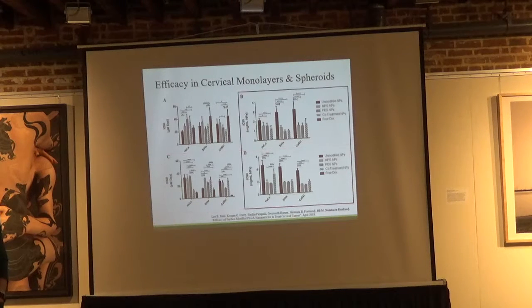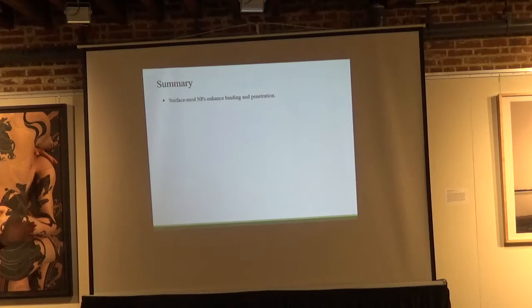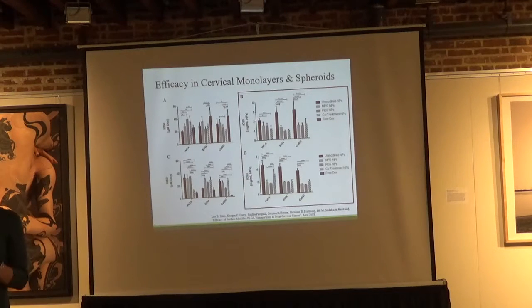And one thing from all of this that we saw across the board was that when you make particles with these small hydrophilic encapsulated agents for delivery to tumor cells, while we can achieve from a particle loading basis, the MPG, PEG, and co-treatment particles across all cell lines were more efficacious than unmodified, this is also very tightly governed by how much you can load into the particle and how much is released over time. So I wanted to provide this backdrop so we can understand why we need to develop particles that have better release and reproducible loading characteristics.